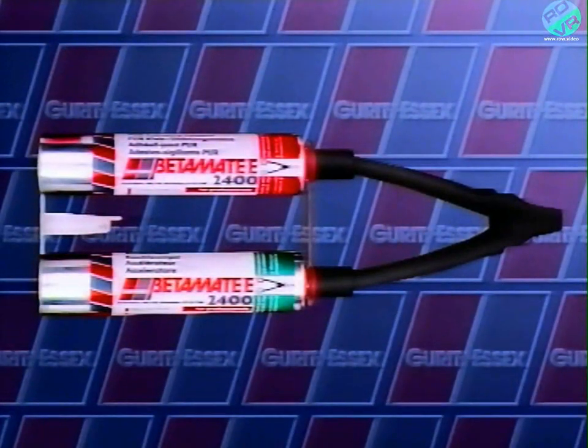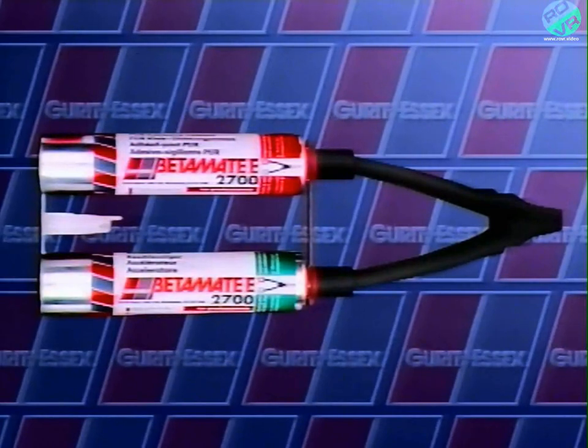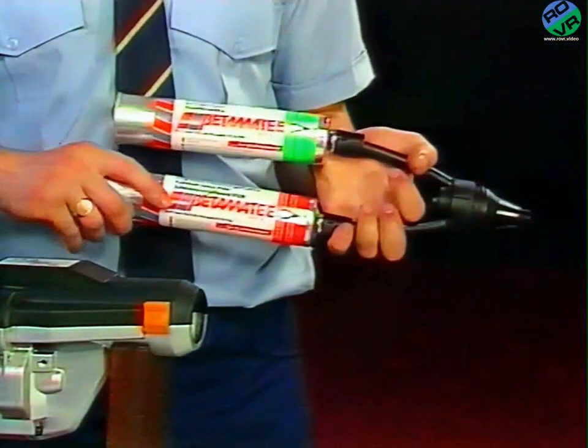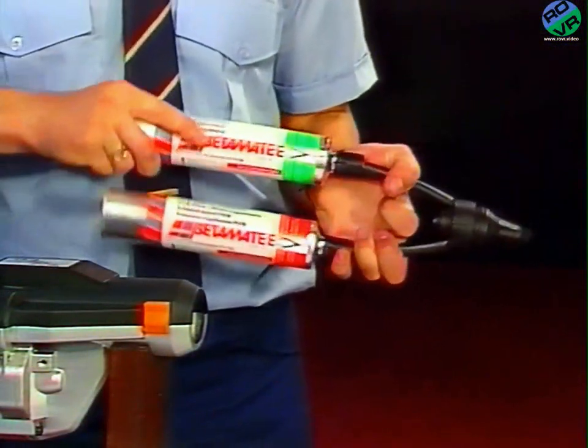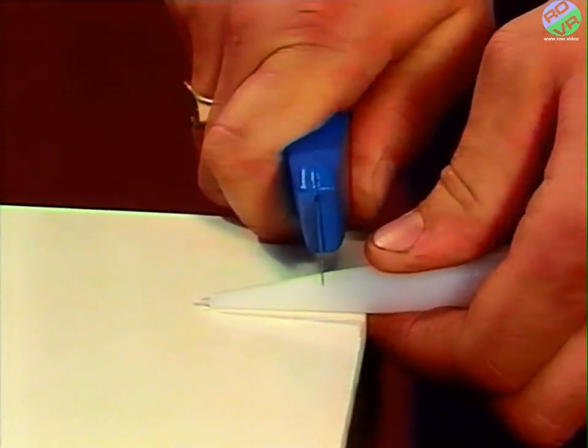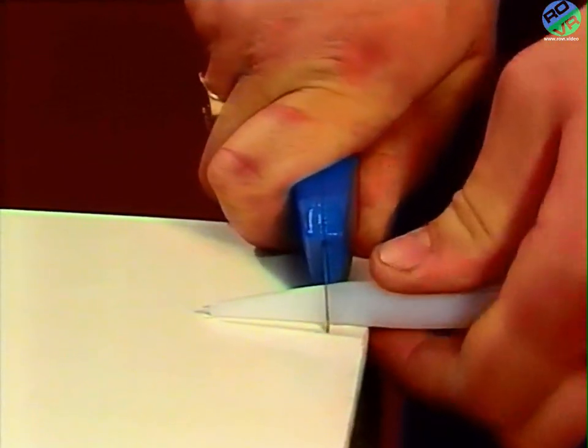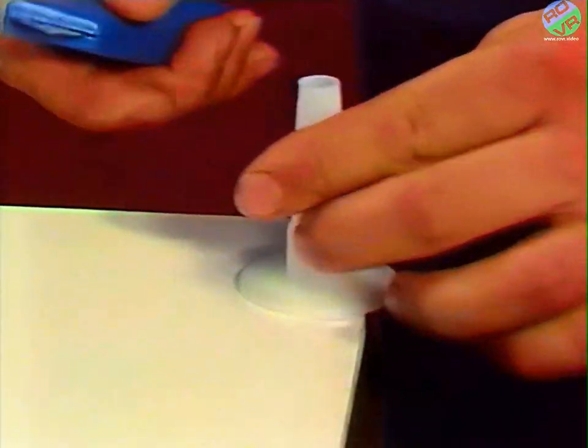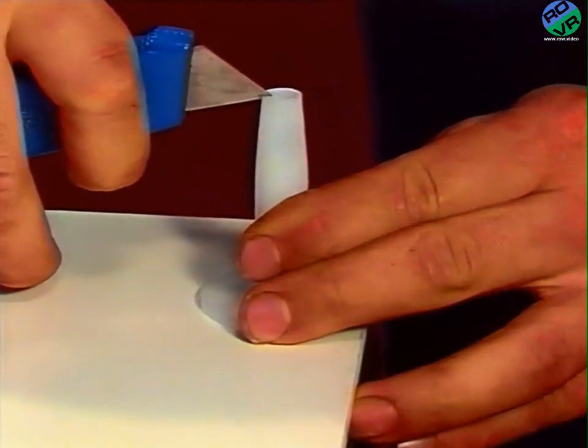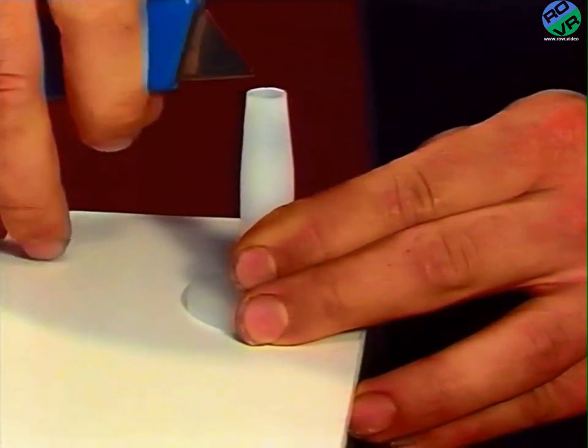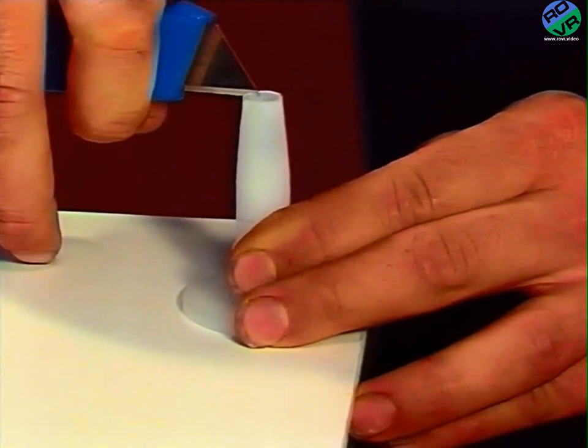Remember, Betamate E2400 for up to 10 minutes working time, and Betamate E2700 for up to 30 minutes working time. But whichever one you choose, make sure that the cartridges are firmly fixed to the mixer head. Cutting the nozzle is a knack that comes with practice. 8mm by 12mm should give you the right bead shape for most repairs. But if you need a bigger bead, say for a truck or a bus, you can cut up to 10mm wide.